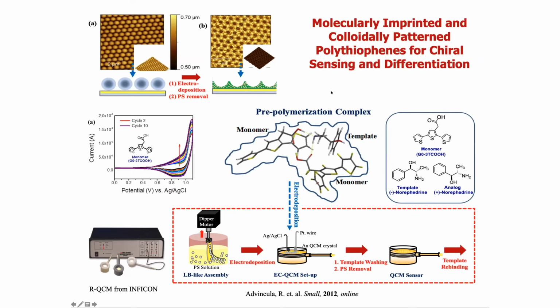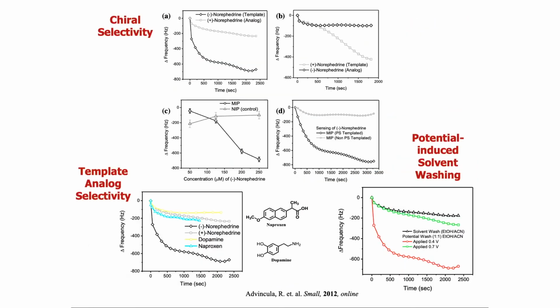And the reason for that is we utilize this for sensing. So the sensing activity was monitored by quartz crystal microbalance experiments. The norepinephrine minus and plus are really enantiomers of each other, where one type of norepinephrine is actually the active drug and the other not. And what this shows is that we can switch between the sensitivity towards one enantiomer over the other simply by varying the template.